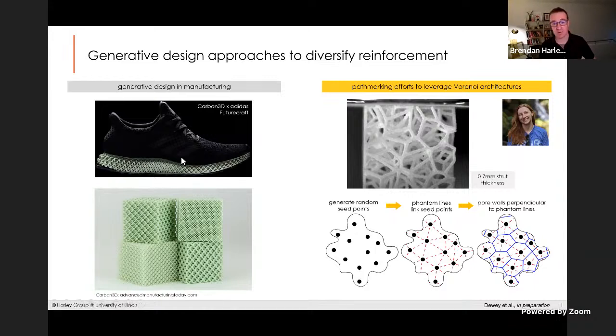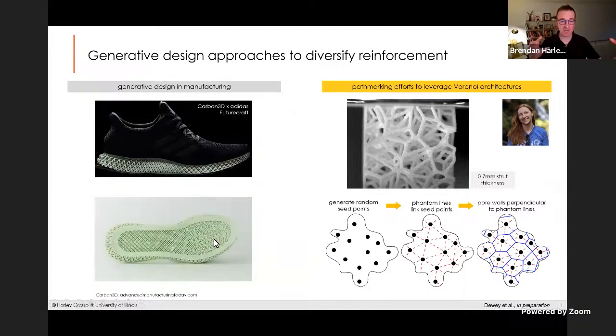So the way they do it, and this is one of the Futurecraft shoes right here, is they've designed different pore architectures that have different porosities, which mean each one of these unit cells has a different strength. And then for Adidas, they made a collaboration where in order to create a shoe sole, they figured out a computational method to stitch together these different pore architectures. So they had stiffer regions and softer regions, and they could print this out as an entire sole. Super exciting, not quite what we're doing, because one of the challenges that Adidas has to deal with is that if they want a size 8 shoe versus a size 13 shoe, they have to print different soles.